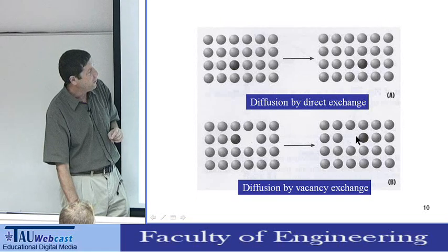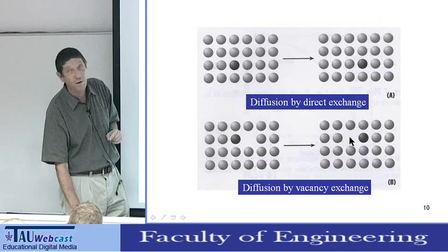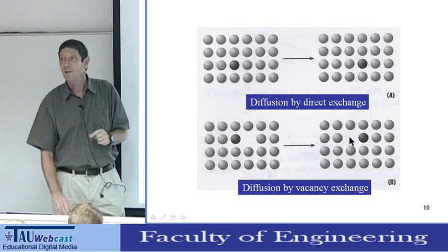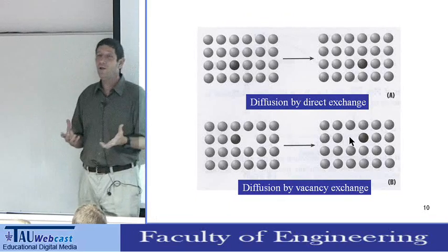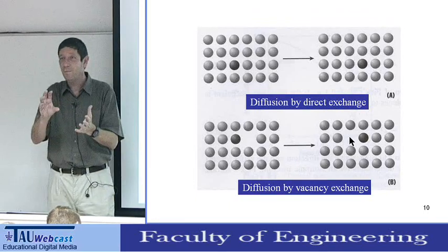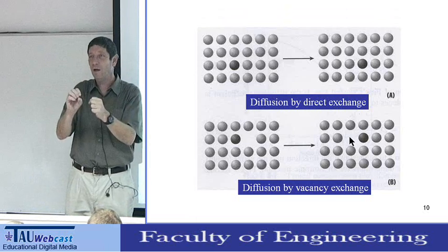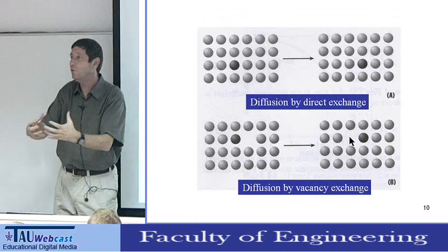Or, after the motion, this can move back, but there are three other possibilities which are in favor. This is called correlation. Basically, the motion is not just the probability to jump, it is to look at all the possible mechanisms and to choose the one which actually contributes to the total motion.